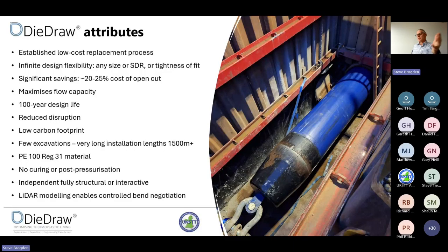We've got a 100-year design life. We've got all the good things about PE100. Very little reduction in bore. We do need a couple of pits. It's a very low carbon footprint compared with open cut. And we can install extremely long lengths, and we're working on increasing that. They were very important in the subsea market because we needed to install long lengths. We installed a water injection line once, 1,500 meters in 2.5 hours. So you can really go at 10 meters a minute if the conditions are correct.